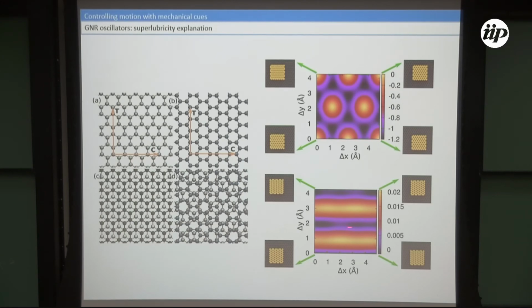For the case on the bottom here, it's a bit different because when you displace the graphene that's on top, some atoms will gain energy, some will lose energy, but there's no real net gain of energy in this kind of displacement. So for the most part, if you look at the scale of energy here and here, it's much smaller here. And if I actually make it bigger, this kind of energy here won't increase. For the top case, the bigger the graphene is, the bigger will be the interaction, this kind of energy gradient that I found here.